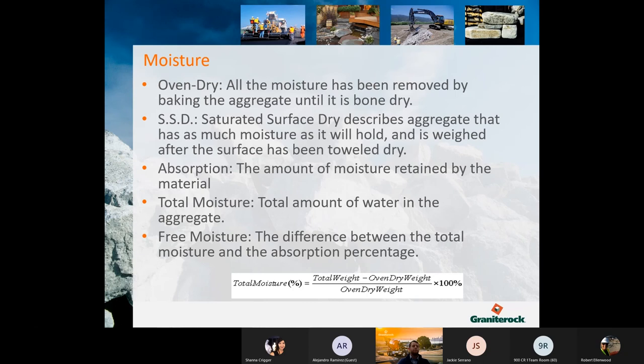When talking about aggregates, moistures really have to be considered. This is more on the batching side, but to understand our process, we first have to understand some of the different moistures that go into aggregates. Because when you make concrete, it's sold by volume, but through our plant, we have to do it by weight. And the moisture in the rock really affects how much it weighs, as well as how much free water is going on. So we monitor the moisture to make sure that the correct amount of water is getting into the concrete.